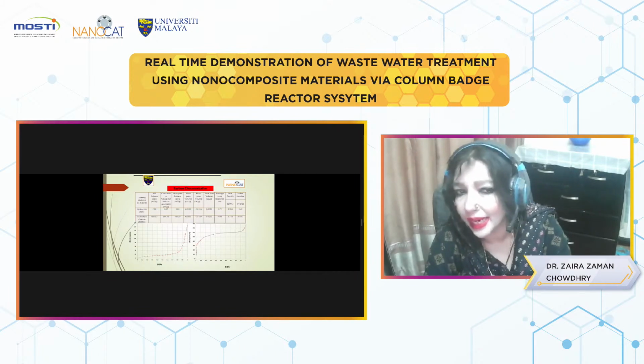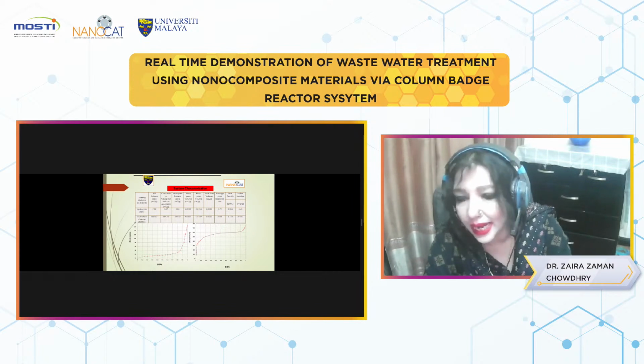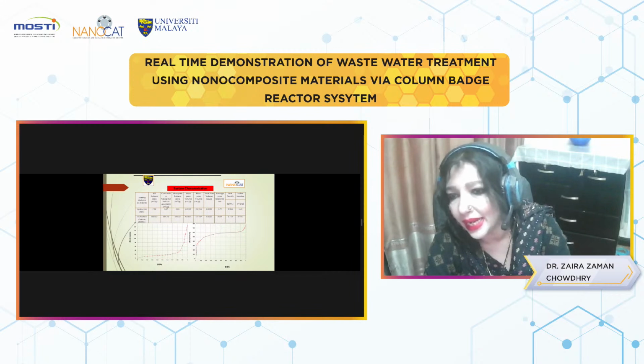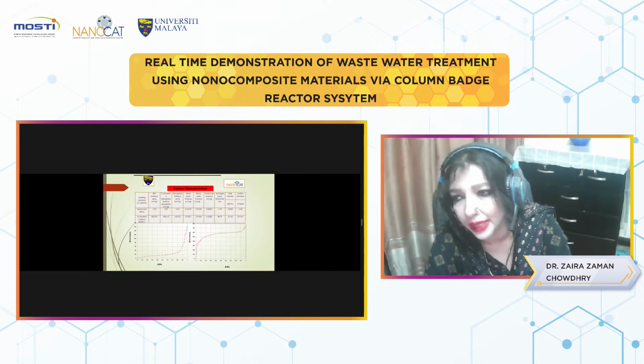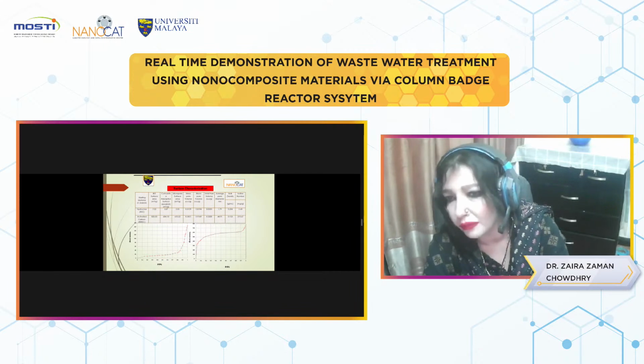So this is our surface characterization. We can see the hydrochar has a surface area of only 7.02. After activation, it became 825.50. And as I mentioned earlier, the second graph is showing an L and S mixed pattern, isotherm for nitrogen gas adsorption in BET, which means that our sample has some proportion of micropore with some mesopore inside it.